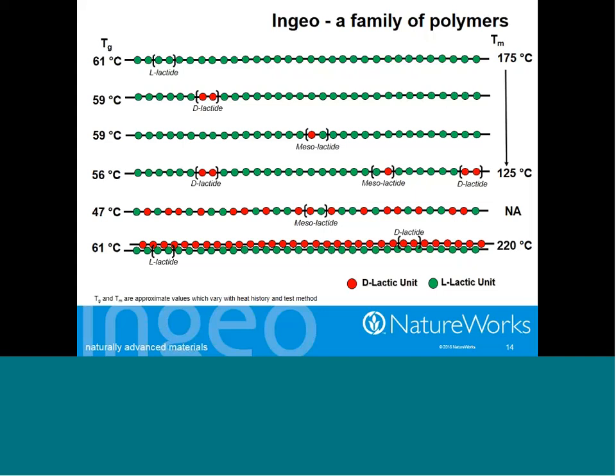The bottom configuration there is what people would refer to as stereocomplex, and that can be made from a blend of what I will call PDLA, so poly-D-lactic acid or poly-D-lactide, and PLLA or poly-L-lactide, or it could even be a block copolymer made from those materials, as long as the block length is in excess of about 40 units. That material will crystallize to give a much higher melting material of about 220 degrees.